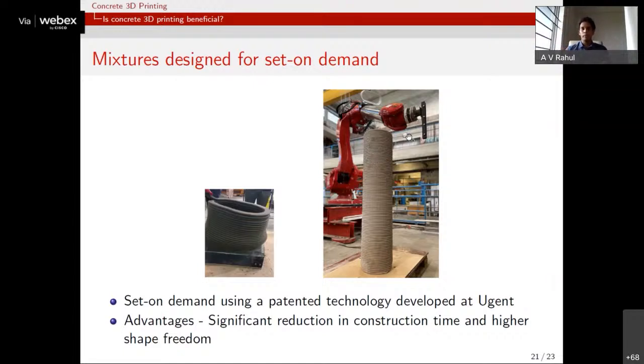Now, in 3D printing, there are several conflicting requirements. One of the conflicting requirements is that between extrusion and buildability. So, for good extrusion, for the concrete to be easily pumped up to the nozzle, it has to be as flowable as you can. But once it has exited from the nozzle, it should have a very low workability. It should stiffen very quickly so that you can build more layers on top of that. So the material requirement before extrusion and after extrusion conflict with each other.